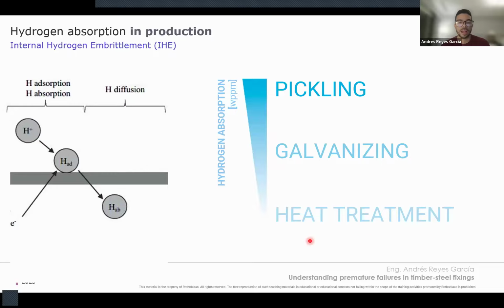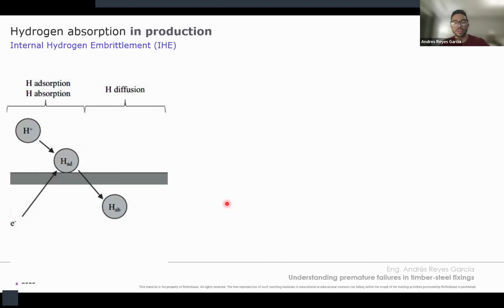Why does that happen? There are many processes that can induce hydrogen, but none of them are as relevant as these three. And even from these three processes, from heat treatment to galvanizing to pickling, the most important one is definitely the pickling process, which is one of the processes during electroplating where the fasteners are put into acid baths that induce the absorption of hydrogen.